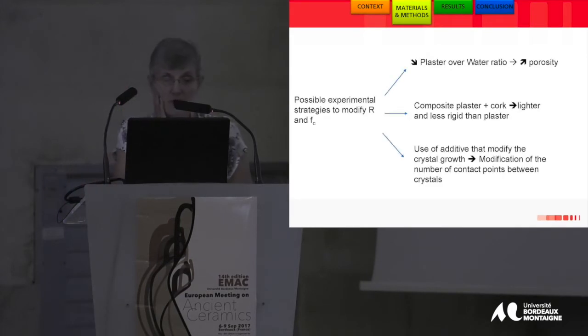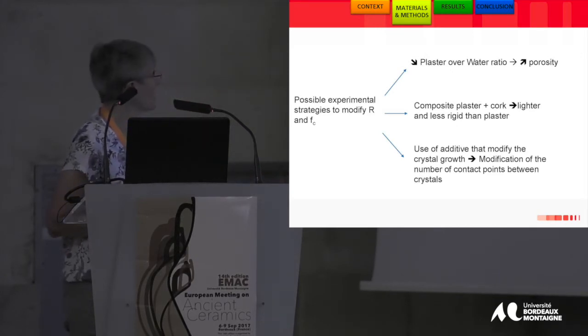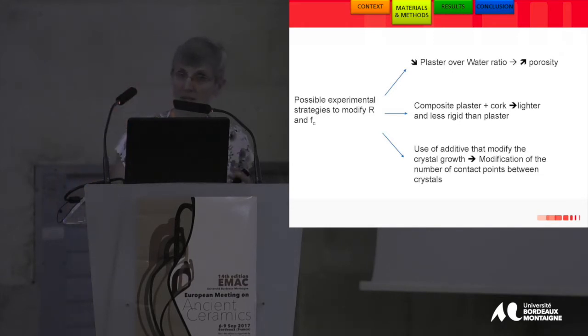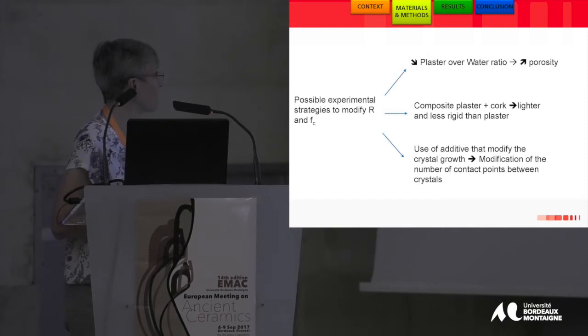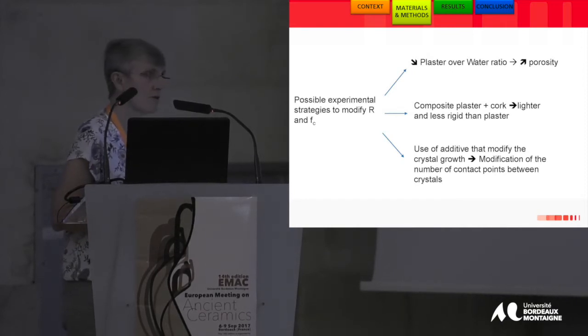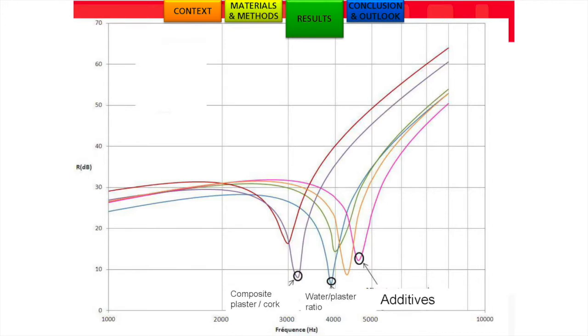So what were the possible experimental strategies we explored to modify both R and the critical frequency? The first one was to change the plaster over water ratio, in other words to dilute the plaster more, meaning Young's modulus should decrease, the porosity should increase, but the critical frequency should also increase. The second strategy is to make a composite between plaster and cork, something lighter, less rigid than plaster. The third strategy is to use an additive to modify the crystal growth, and by this we managed to modify the number of contact points between crystals.